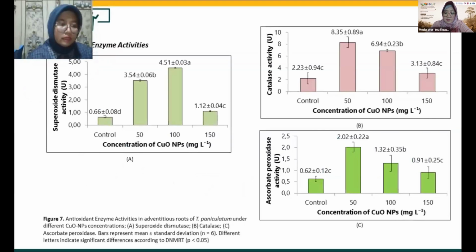5. Antioxidant enzyme activities. Copper oxide nanoparticle elicitation significantly affected the activities of antioxidant enzymes in adventitious roots. Superoxide dismutase activity increased sharply with copper oxide nanoparticle concentration, reaching its maximum at 100 mg per liter, see Figure 7. Catalase and peroxidase activity exhibited peak values at 50 milligrams per liter, followed by a gradual decline at higher concentration. At 150 milligrams per liter, the activity of catalase decreased substantially, although it generally remained higher than that in untreated plants.